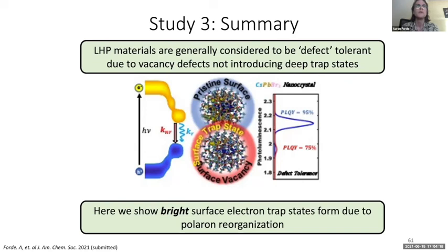There have been publications that it is size dependent, and the Stokes shift grows larger with decreasing size of the nanocrystal. So it could be that in the non-polaronic state, it absorbs, and then after nuclear reorganization, it lowers the transition energy to give the overall Stokes shift for the small nanomaterials.